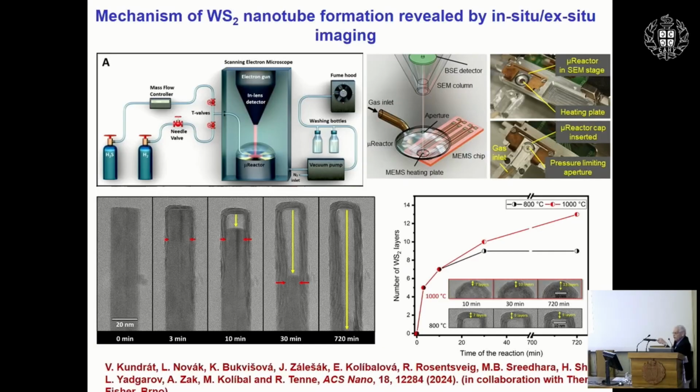Before, we always thought that the hydrogen sulfide comes from the outside and goes inwards, like you can say the Kirkendall effect, but now we see that there are also remains of the tungsten oxides, since it's engulfed by tungsten sulfide layers, there is tungsten oxide also in the core, and consequently, they react with the hydrogen sulfide that goes into the core, and the reaction progresses inside.